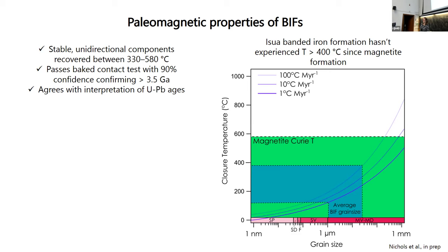Just a technical question on that - dating the magnetite, can you do this spatially resolved, and how little magnetite do you need? Yeah, so we're doing this with SIMS at the moment, mapping out in individual grains where the uranium and lead is, because it's a bit of a controversial system - we don't think there's much radiogenic lead in that and we don't know where the uranium is. So we're doing mapping at the moment in individual grains, similar to what people have done with carbonates - you can map out your uranium-lead distribution within a single magnetite grain. The original was Tim's work, so you know where to go with Tim's and then you can get more accurate results. Watch this space.